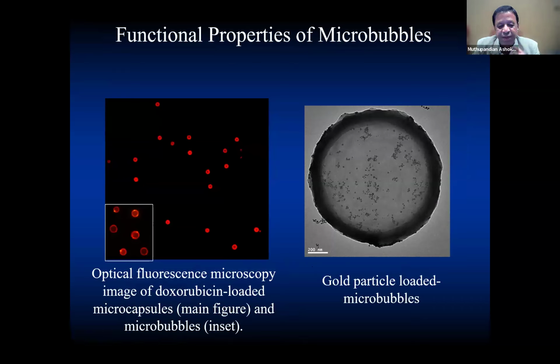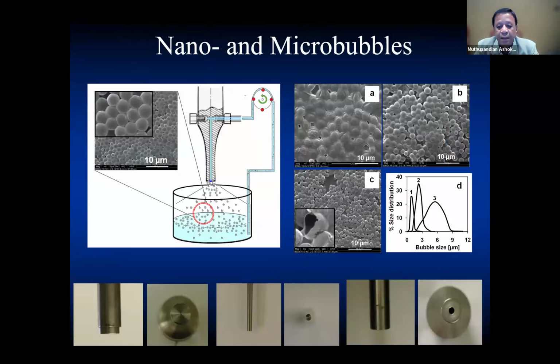The difference between simply injecting doxorubicin compared to the microspheres is that when you simply inject into the blood, it goes everywhere. But when you inject through these microspheres, we can functionalize them and make them deliver locally where they have to be delivered. So it's a targeted drug delivery process. We can also load these microspheres with some metal particles, which have antimicrobial activities. Again, we can use them for biomedical applications.